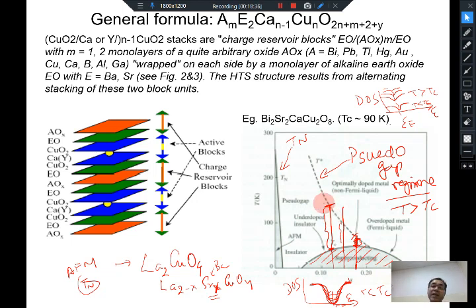So the pseudo gap phase is a very interesting regime for superconductivity, and there has been a lot of work which has gone into trying to understand it, because you can see that this pseudo gap phase can actually survive up to very high temperatures, even reaching up to room temperature. So you don't have phase coherence in this regime, namely you don't have dissipationless flow of current, but nonetheless there are some Cooper pairs which are still present. They are locally present, but globally or macroscopically there is no uniform density of Cooper pairs which are all in phase with each other. That does not exist. So the pseudo gap phase is a very interesting aspect of high temperature superconductors.